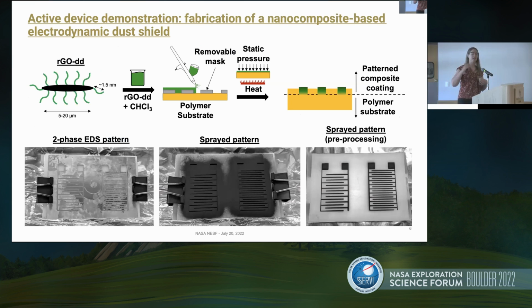We took an approach that is just a very simple masking approach. So it's the exact same process, except in the spray process, we insert a removable mask. In the bottom images, you'll see before deposition, just a mask clipped to the substrate. And then we spray over the mask, we remove it, and then we follow the same processing steps to basically make nanocomposite wires that are integrated into the polymer substrates.